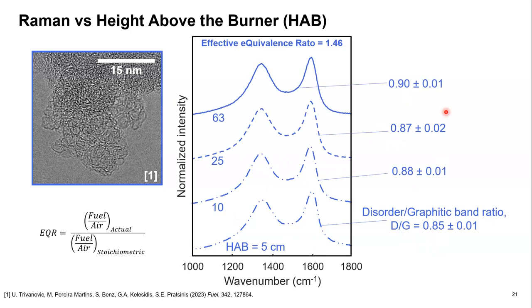So what this shows us is that from 10 centimeters onto the exit of the flame, this was relatively constant, and we had a slight increase in the amount of disorder going from 5 centimeters to 10 centimeters height above the burner. What this confirms is what we saw on the last slide, that in particular, after 5 centimeters height above the burner, we do not have a significant contribution from surface growth because these Raman spectra are fairly unchanged.